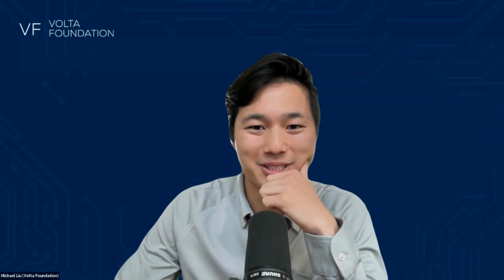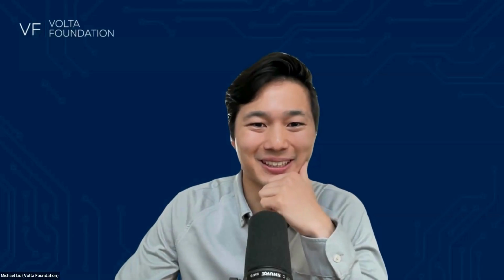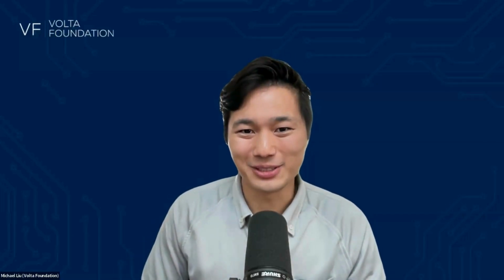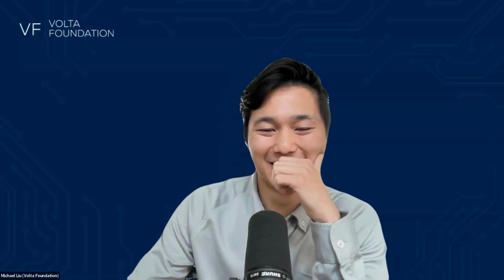Oh man, we have Tristan here. I'm really hoping Tristan can give some insight. He's from Exponent, so that's his expertise. So we do a lot of modeling of failures and of thermal failures, and the Weibull modulus of thermal failures is typically greater than 1, and so that suggests that your hazard of failure is increasing over time. So I would say that older packs are more dangerous, just based on what I've seen.